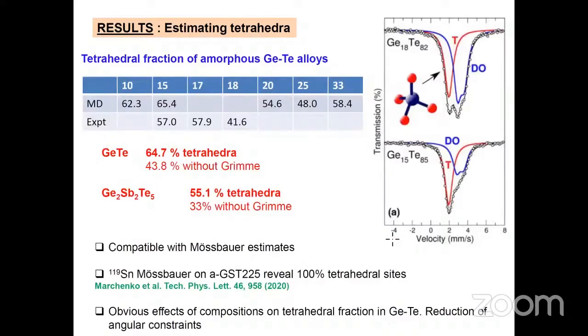And so we can go through effects of composition. Here, for example, in the binary GeTe, we see that the fraction of tetrahedra evolves with composition. It can eventually be compared with an estimate from Mössbauer spectroscopy, which has a typical signal if you have a tetrahedral site, using tin-substituted Mössbauer. I should also signal that if we do this on the phase change materials GeTe or GST, we find indeed that GeTe and GST are dominated by a tetrahedral geometry. And again, if you do the same simulation without Grimme, then in this case, this fraction is substantially reduced. So this is also in line with a very recent Mössbauer spectroscopy on GST that has revealed that the tin substitution reveals 100% tetrahedral sites.